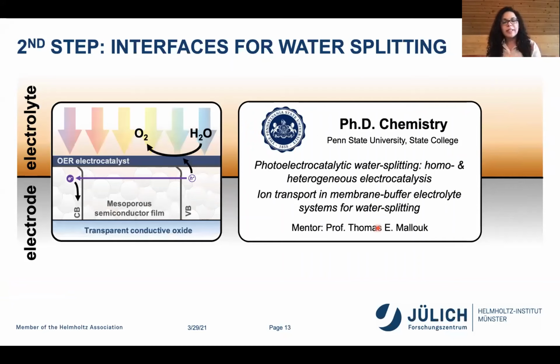That drove me to my second step. This is where I went to Penn State to do my PhD in chemistry under the mentorship of Tom Mallouk. During my time at Penn State, my PhD focused primarily on photoelectrochemical water splitting interfaces. This is how that looks. We had a transparent conductive oxide, fluorine-doped tin oxide, for example, modified with a thin film of a mesoporous semiconductor film. In our case, it was mostly n-type titania, TiO2, where we modified the surface of the titania with an oxygen evolution catalyst so that we can transform water to oxygen in a way that is entirely driven by light.